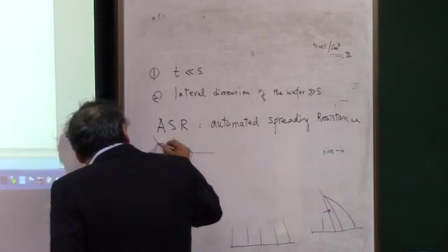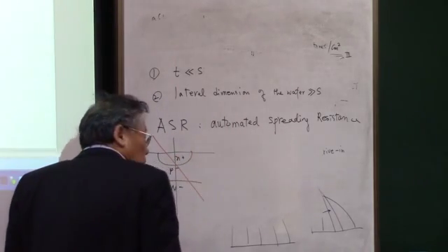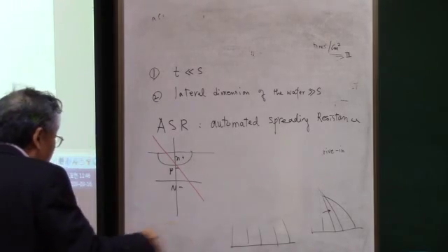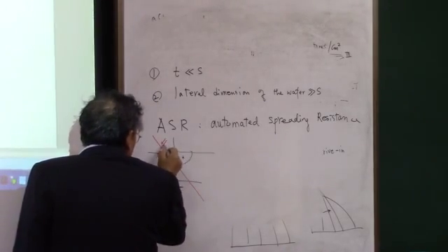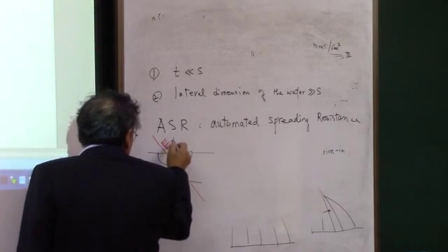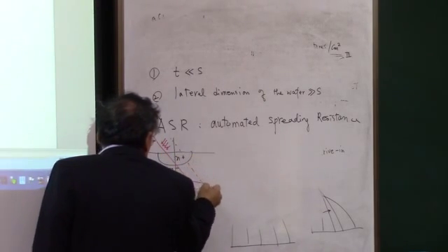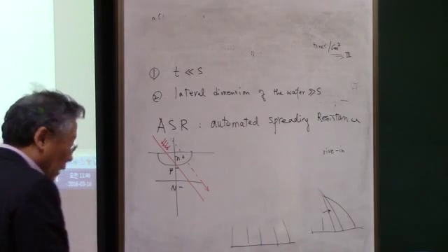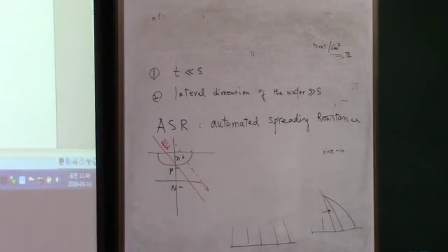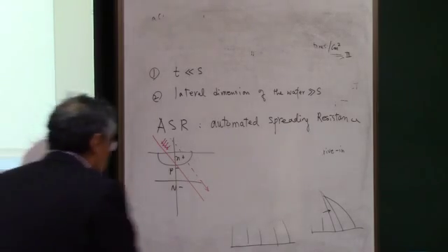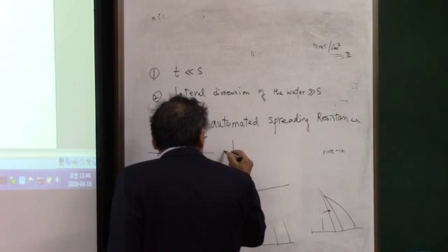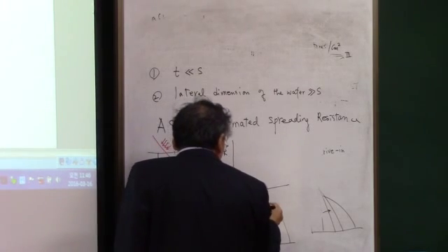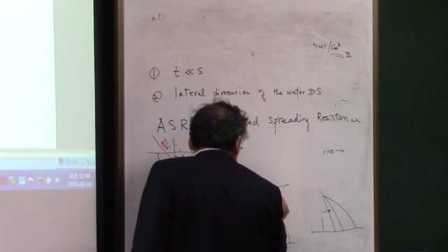We polish at some angle so that we move the probe along these directions, and then we convert that to the resistance with the distance, okay?